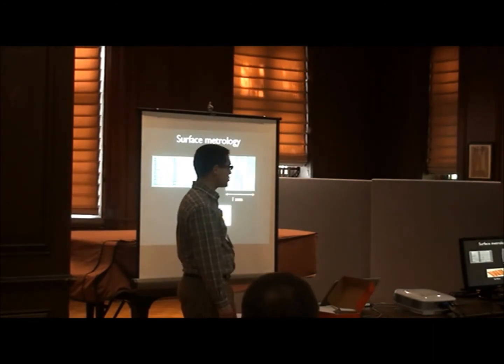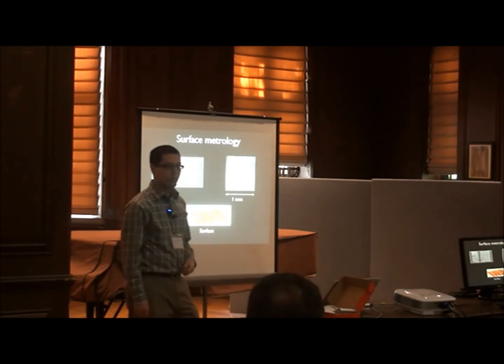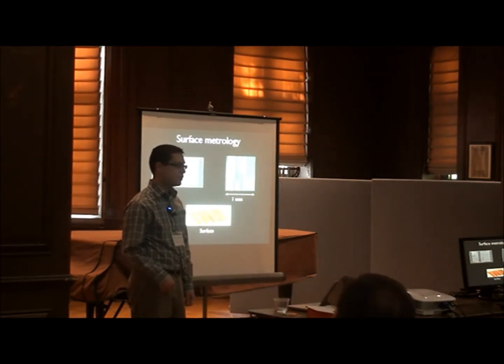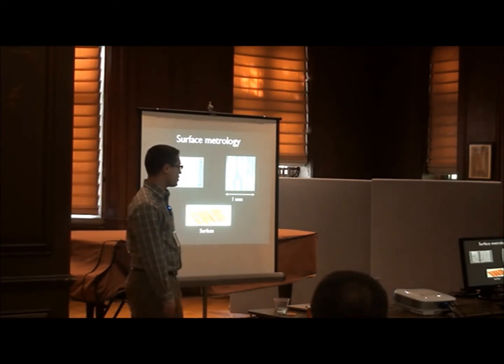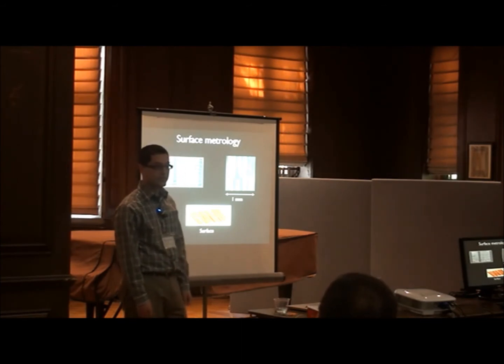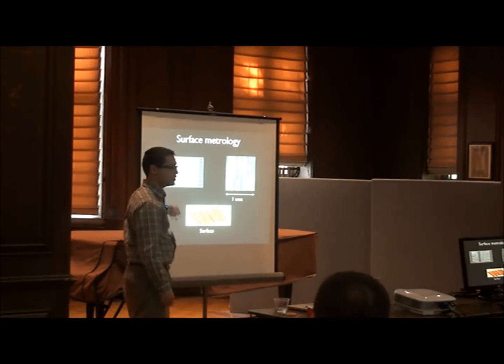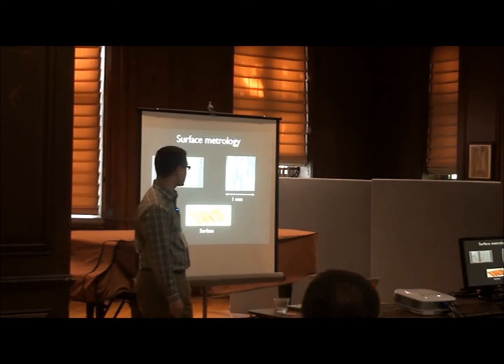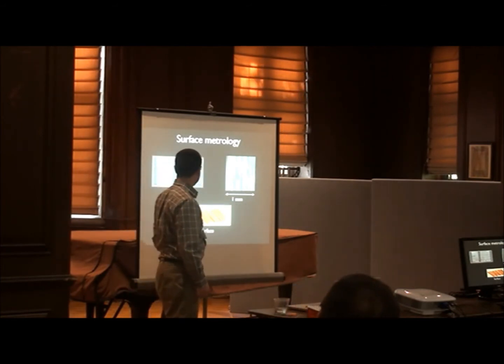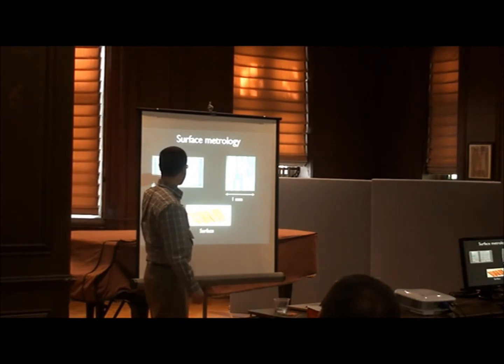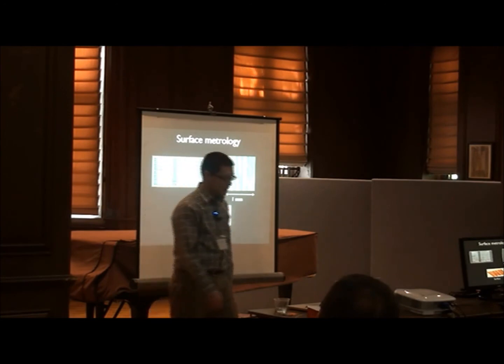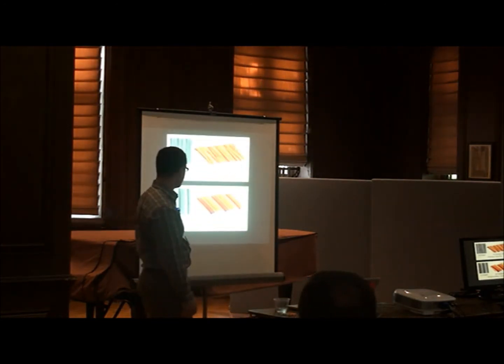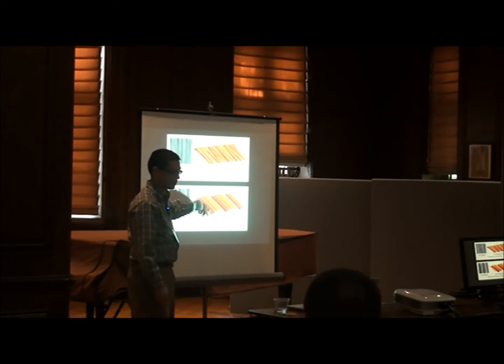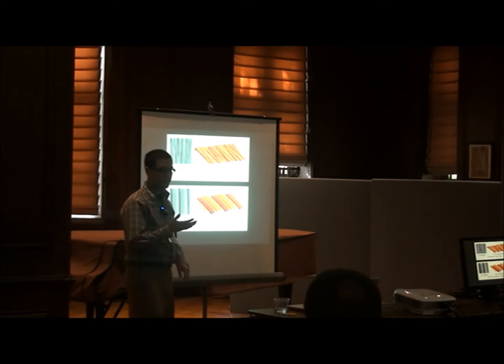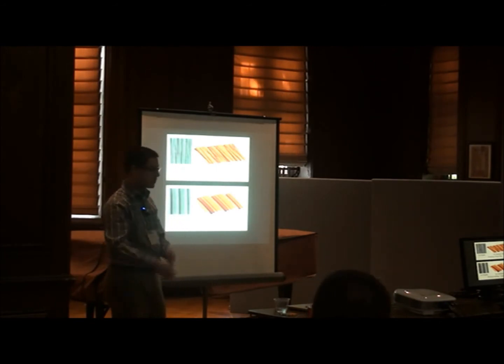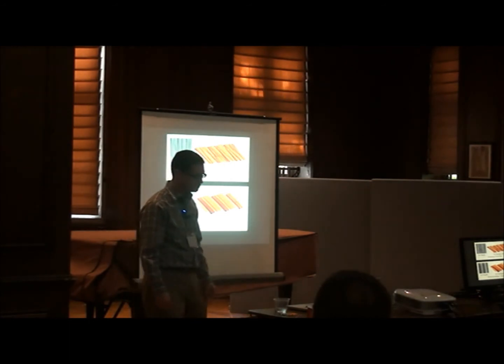Finally, a few slides on surface roughness measurements. When people started approaching us, asking us if this could be used as a surface roughness tool, or what our capabilities were in that space, somebody suggested very early on that we buy a surface roughness gauge and do some sample measurements of it. So that's what we did on these slides. This is 1 millimeter square from this grinding 0.8 micron Ra patch, a false color rendering of the surface. Here's grinding compared to vertical milling, and you can certainly see the difference in surface topography. These are depth images, so bright pixels are high and dark pixels are low in depth, but the false color rendering is easier to interpret.